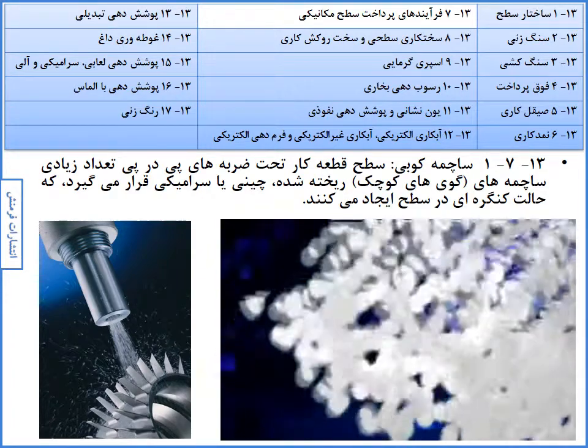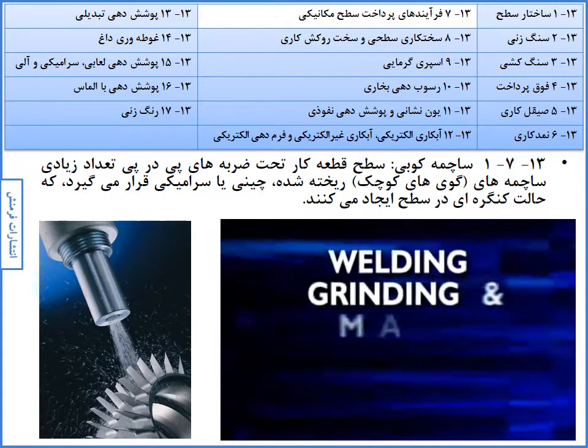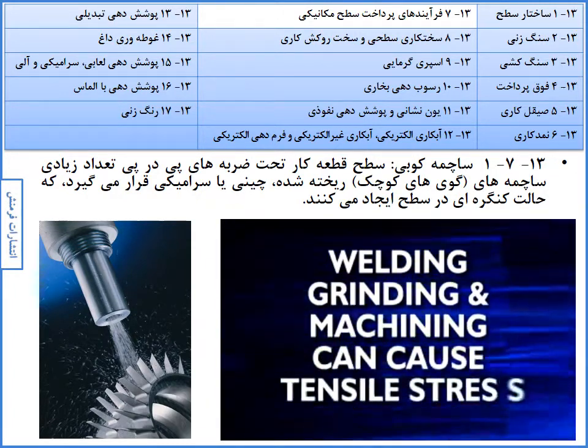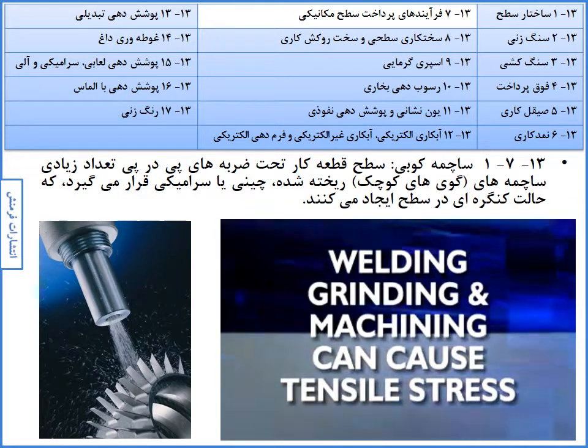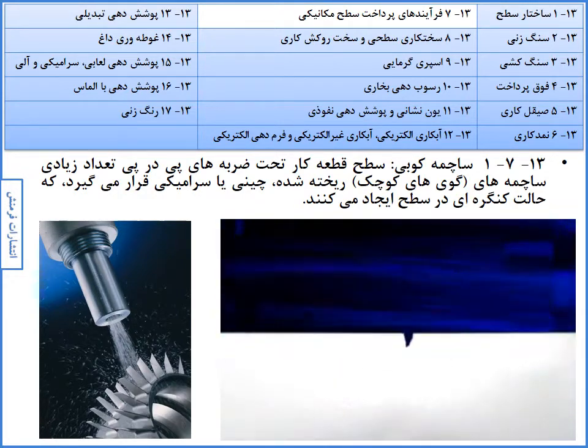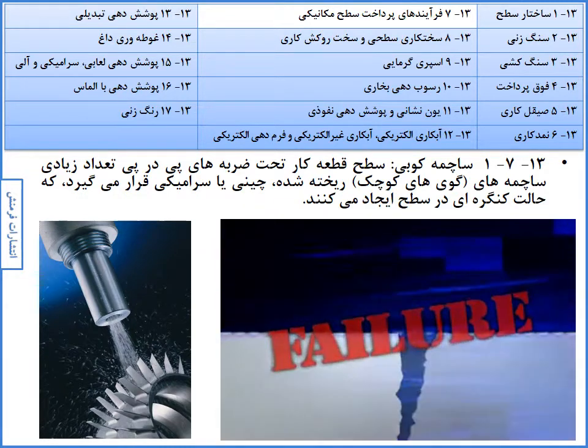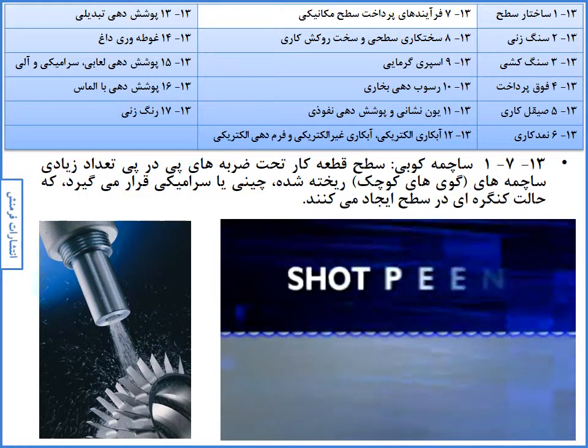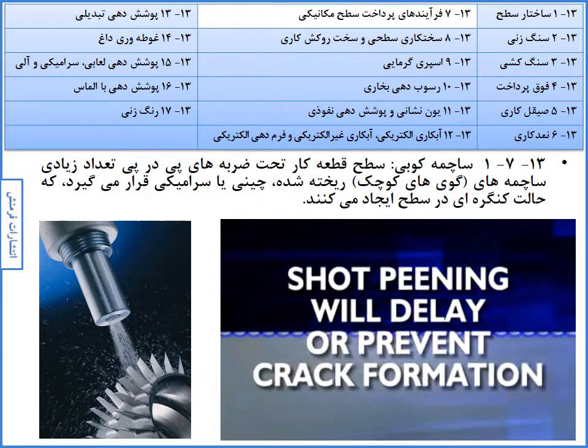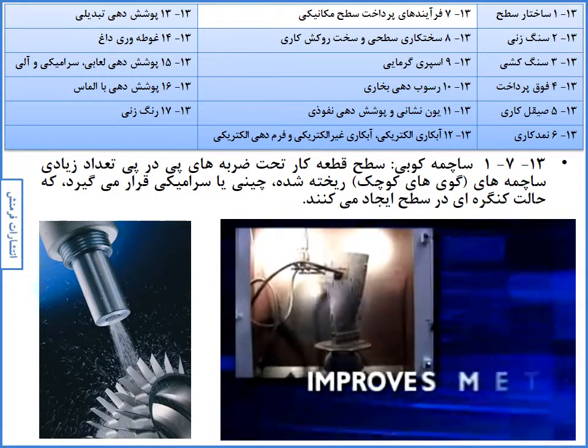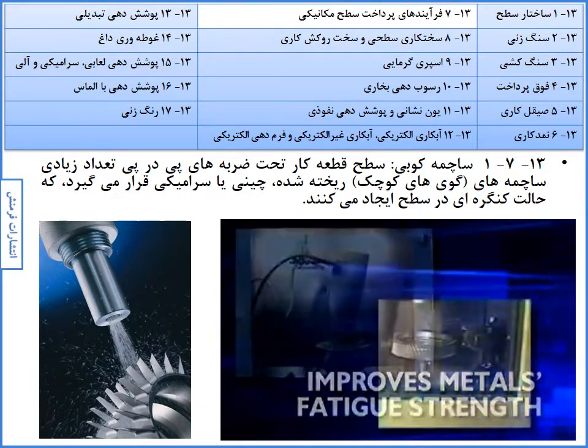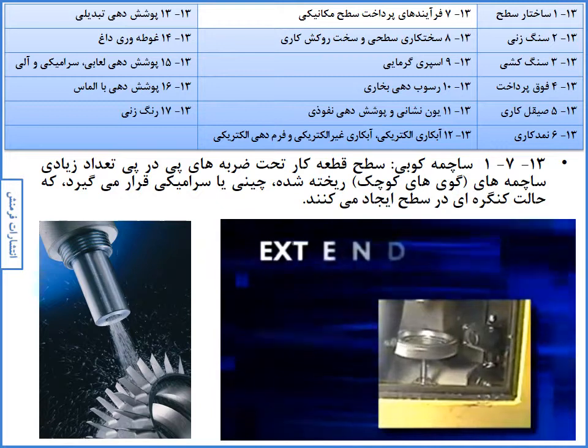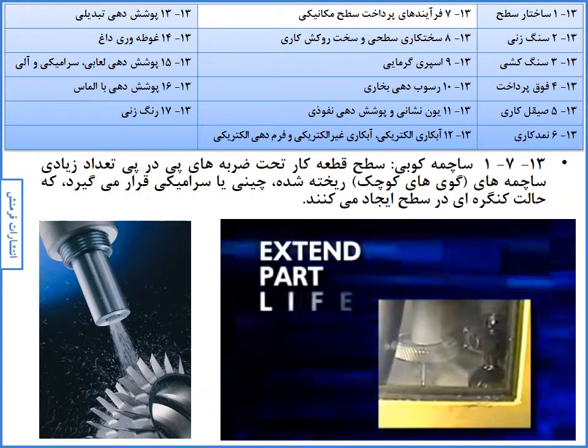External loads and manufacturing processes like welding, grinding, and machining can cause tensile stress on a metal surface. Those tensile stresses attempt to stretch or pull apart the surface, which can lead to cracking and part failure. However, the compressive stress from shot peening will significantly delay or prevent crack formation in the compression zone. The deeper that stress layer, the more resistance to cracking. In fact, the residual compressive stress produced by shot peening displaces the tensile stresses that lead to fatigue failures. The net result? Compressive stresses induced by shot peening provide significant increases in component life.